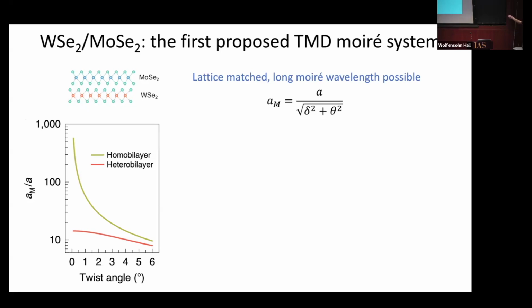in many of the previously studied samples, if you use different transition metal dichalcogenides, they may have different lattice constants. And so the Moiré wavelength depends on both the lattice mismatch and also the twist angle of any system. And when you have a heterobilayer, that means that as you decrease the twist angle, eventually this lattice mismatch term is what's dominating, and it limits the Moiré wavelength that you can get, even if you go toward the zero twist limit.